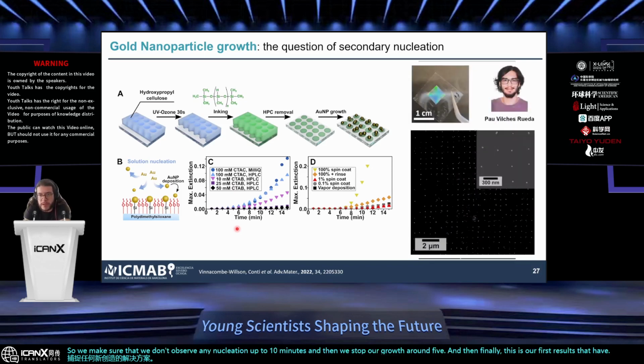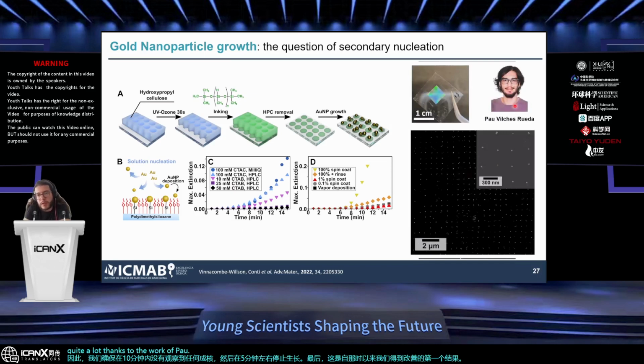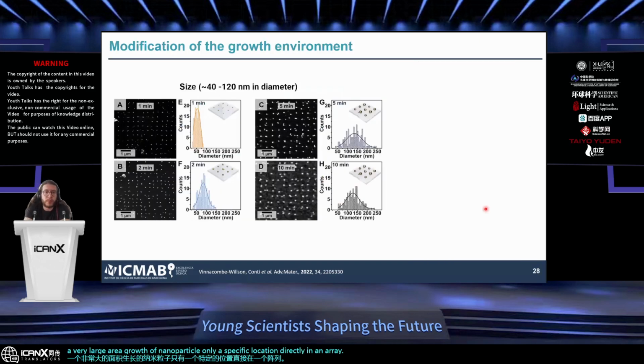And then finally, this is our first result, which has since improved quite a lot thanks to the work of Pau, who recently joined the lab. As you can see here, we're now getting to the point where we can have large area growth of nanoparticles only at specific locations directly in an array. We prove the flexibility of our system by changing the size, by varying the time of growth, and also by changing the shape.